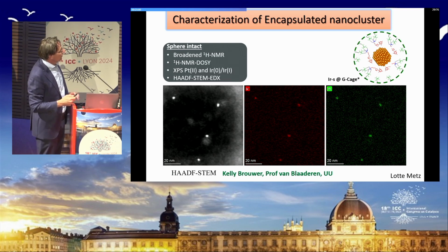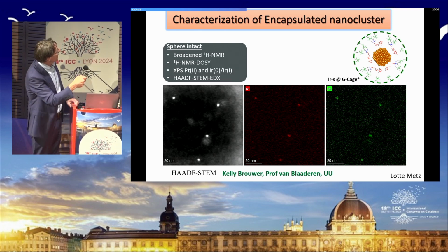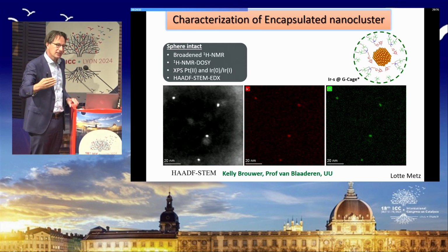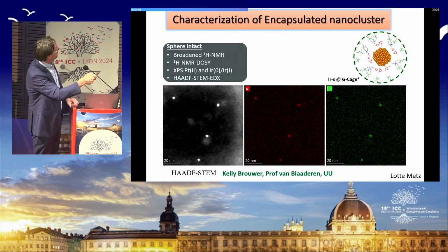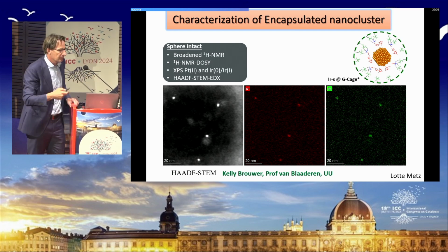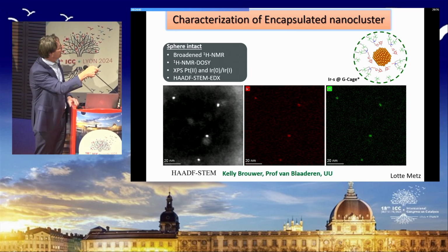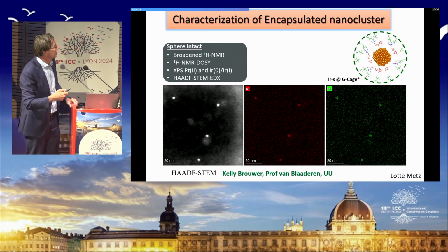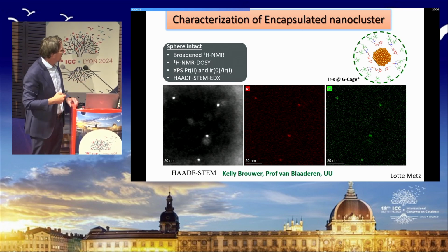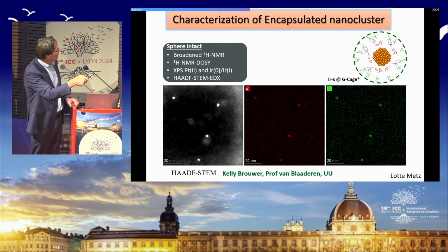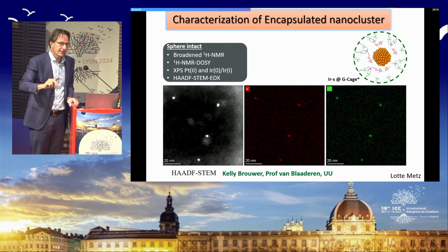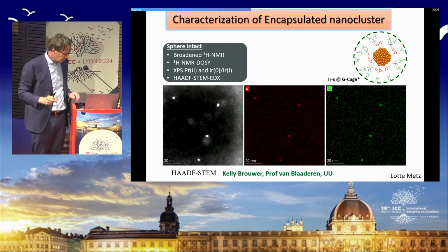So next we wanted to prove that the spheres are still intact, so we still see the NMR, although broadened because of the nanoparticle. We can do NMR DOSY, showing that the cage is the same size as before the reduction. XPS shows that the platinum is still in the oxidation state 2, and iridium is mostly in iridium 0, although still some iridium 1 is present. And these are the HAADF-STEM pictures, where we show here that iridium and platinum coincide, indicating that the iridium is still in a nanoparticle.